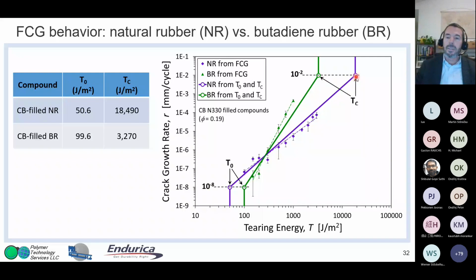So here's natural rubber, 18,000. Here's butadiene rubber, 3,000. You can plot those two data points on here. And then you could do the same at the low end. And what you see is butadiene rubber is here and natural rubber is here. And if you just draw a straight line between them, it almost captures the actual fatigue crack growth data that were acquired from testing. So this was a sign that if you know the two ends, you know the tear strength at the upper limit, and you know the fatigue threshold at the lower limit, that knowledge can give you an approximation for what's happening in between, and you can even reproduce the crossover simply by drawing a line between those 2 points.